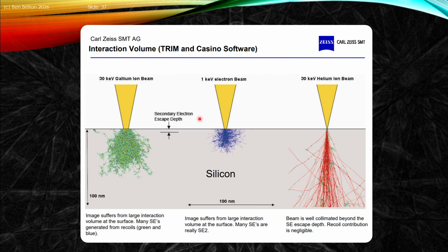Now, why would you want to change your source types? Well, you might want to, for instance, improve your spatial resolution. So gallium FIB can produce effectively a 30 kV beam, which has a relatively wide probe. It's high energy, so these ions go quite deep into the sample and create lots of damage and interaction. If you drop the voltage, you can make the probe smaller and the interaction smaller. But if you want a really narrow and high spatial resolution, you can improve this by having that very, very narrow source, where we have the 0.35 nanometer source, that can improve the spatial resolution even further.